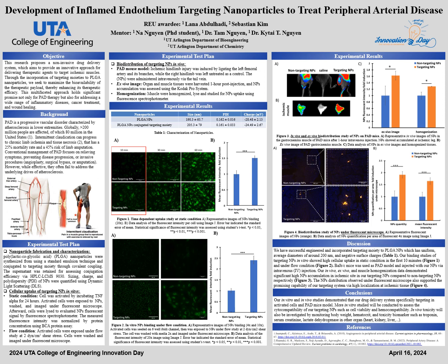Results indicate an increase in size from 190 to 205 nanometers after characterization, suggesting successful binding, along with a change in charge from -28 to -24 millivolts, indicating chemical interaction between the components. Additionally, the PDI value of 0.162 versus 0.161 suggests that both nanoparticles are homogeneous in size.